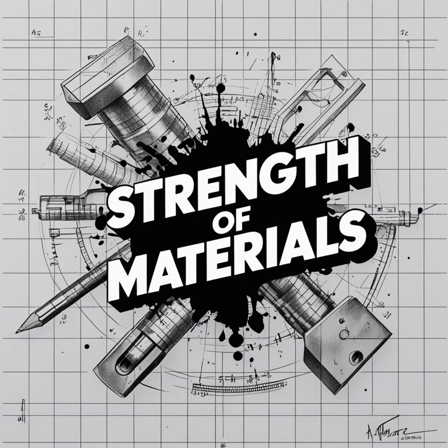Now, you also mentioned earlier that geometry plays a role. This one confuses me a bit. Why would a thick plate of steel behave differently than a thin sheet if they are poured from the exact same batch of liquid metal? It is entirely counterintuitive, I'll give you that, until you visualize the stresses. It's the difference between what structural engineers call plane stress and plane strain. Okay, break that down for me. Sure. Thick, heavy plates operate under plane strain conditions, and they are significantly more prone to brittle fracture. Wait, why? Wouldn't thicker be stronger and safer? Stronger, yes. Safer against brittle fracture?